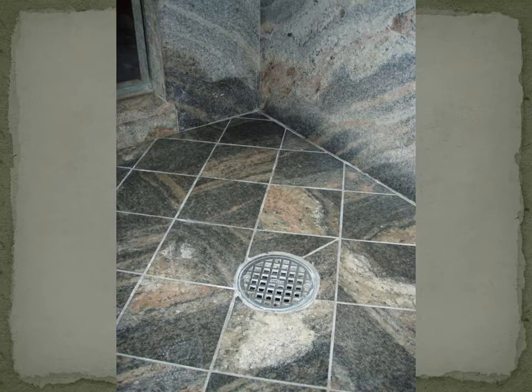This is in a shower. Granite, and it looks like somebody just took a shower, but this shower has not been used for a couple of months, and it is dry. And so this is just the nitrates and the chlorides from the mortar bed, or the alkaline salts from the mortar bed, that is the dry pack mortar, 1-3 sand and cement, highly alkaline, just wicking up into the tiles on the shower floor and starting to wick up the shower walls.